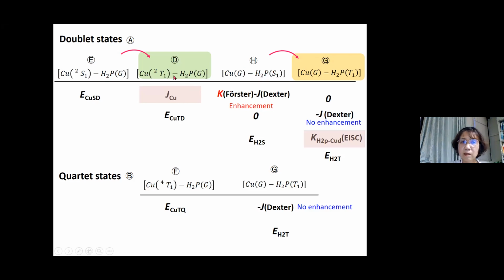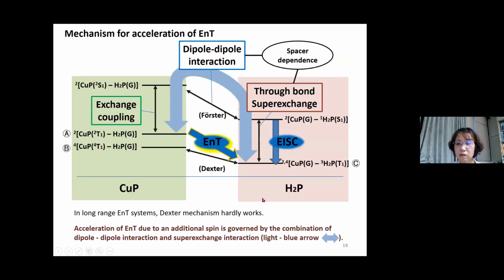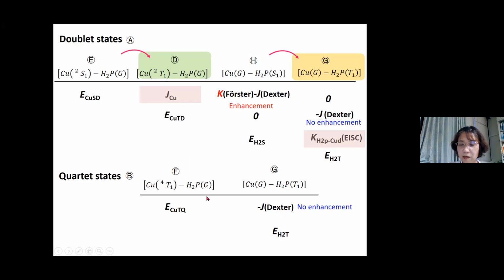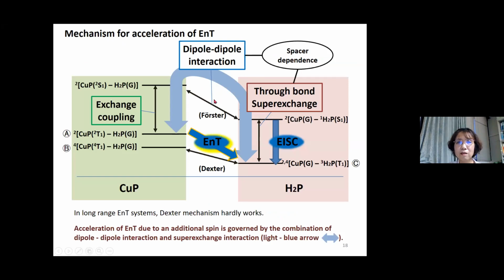So the enhancement is considered to occur between the triplet doublet state and the triplet state of the free base porphyrin through this Förster term, due to the interaction of the upper excited state. On the other hand, in the quartet state, we found that there is no enhancement. We have a matrix element which is exactly the same as in the zinc porphyrin case.